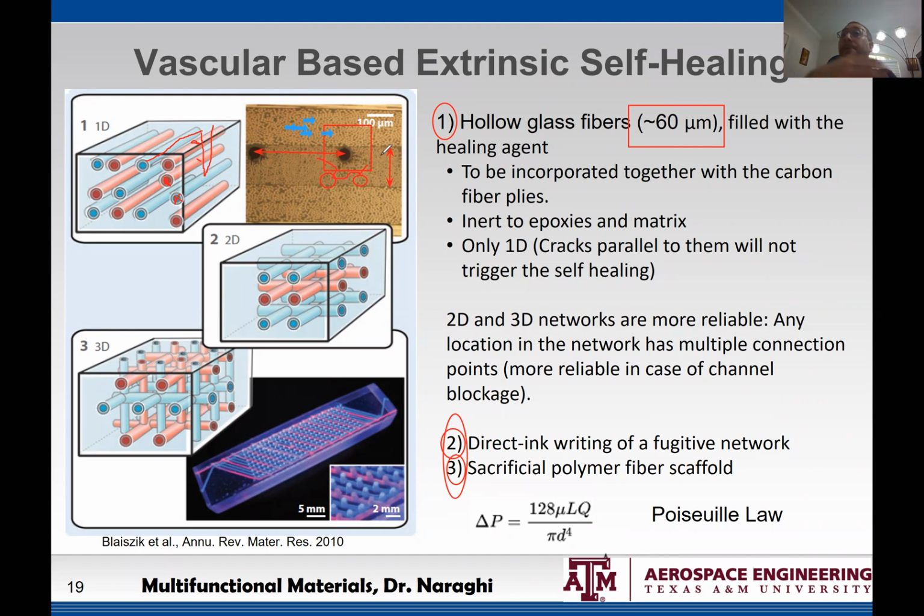In that case, I have to remove a lot of the load-bearing fibers. So some trade-offs exist here. Either I put these large tubes very close to each other so that I can stop and heal cracks with high likelihood, in which case I have to remove a lot of load-bearing fibers, or I put the tubes or holes very far from each other.